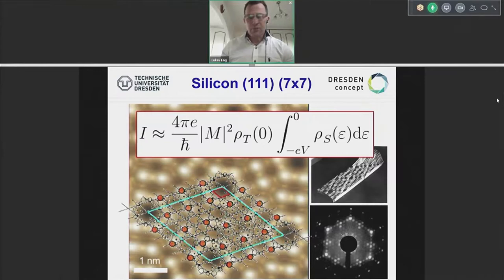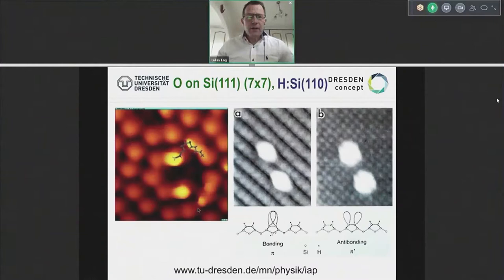Well, there are other things where the chemistry plugs in. Let's take back the silicon 7x7, like shown here on the left side. And that's some kind of oxygen. You see, actually, it is a bright dot, which is symbolizing an oxygen. In fact, it's a measurement. It's not a mimic. You see an oxygen attached to a molecule here. And in fact, what you see is that the density or the probability of electron tunneling increases suddenly because this oxygen is here. Why should this be?